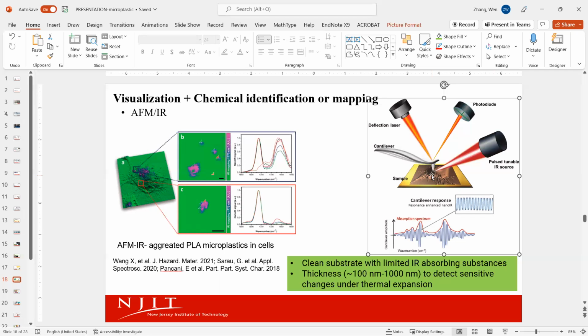So this laser is not a continuous supply, right? You can see this is a pulse. So you pulse it, and then the sample, for example plastic particles, is going to swell and shrink and perform such vibration. And this vibration magnitude is maximized when the IR frequency or wave number matches the actual IR wave number. I hope you understand that. When you use FTIR, you scan the sample using a range of wave numbers or frequencies, right? So when you identify surface functional groups, you have pretty large peaks, right? That indicates the maximum absorbance of the IR signal, basically.